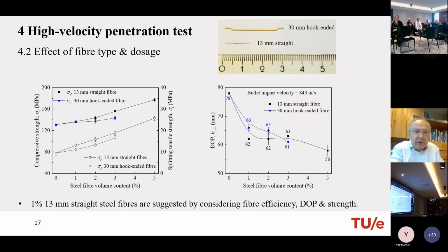Well, here you can see some effects. Here you can see steel fiber volume, also important to control. And here you can see the compressive strength and the splitting tensile strength. And you can also see the straight fiber and the hooked fiber, and perhaps unexpected. Perhaps it's not what you would expect, but the straight fibers performed the same or even a little better, the short straight fibers, than the 30 millimeter hooked end fibers.